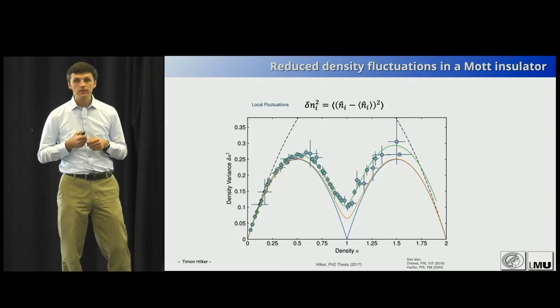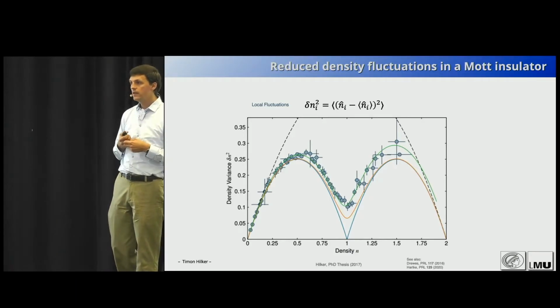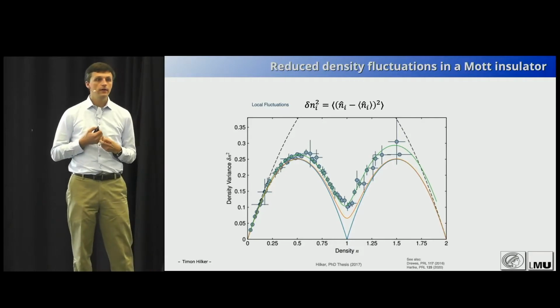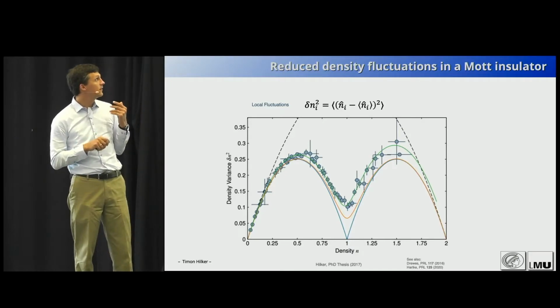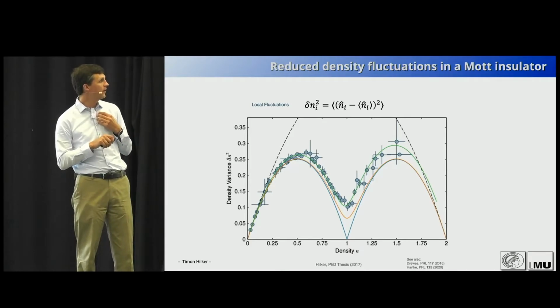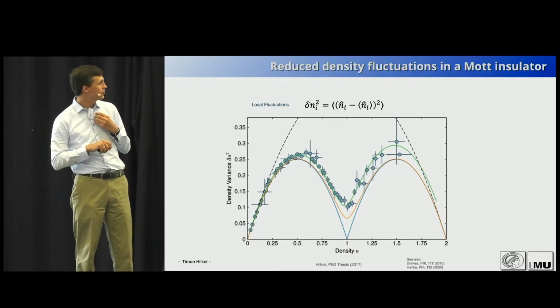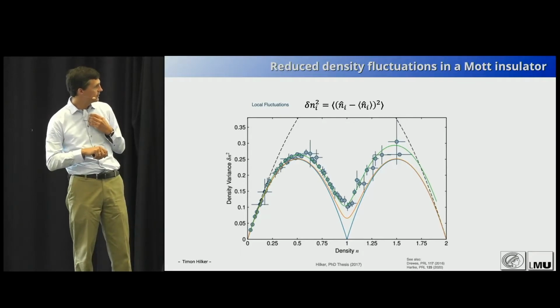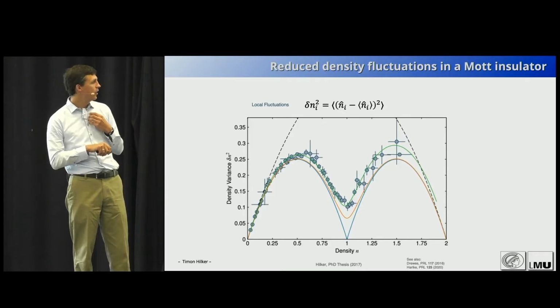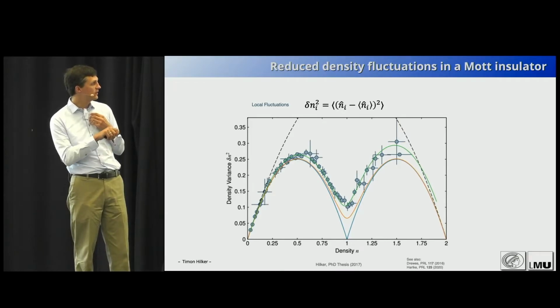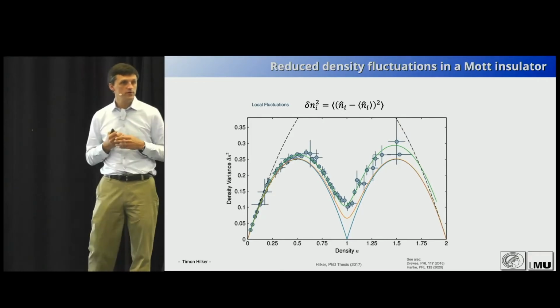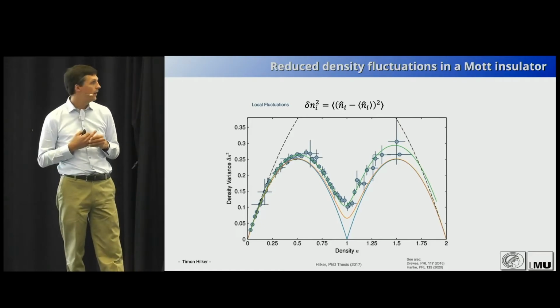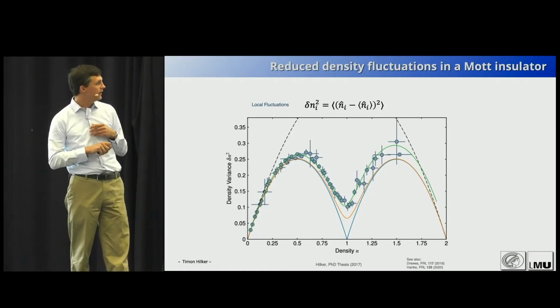But then I mentioned that we see all the fluctuations. So what do I mean by seeing all the fluctuations? It really means that one can calculate something like a local variance over all the pictures. So here is a measurement of this. We see the density going from an empty band to a completely filled band, from 0 to 2, and because of the strong interactions, there's this dip here in the middle where the fluctuations are strongly reduced around the Mott insulator. Theoretically, one could expect to go to 0.